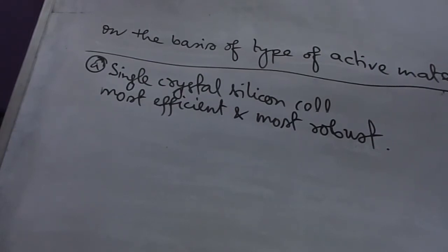The first step is the production of metallurgical grade, 99% pure silicon, MG-Si, from its ore SiO2 by reaction with carbon in an arc furnace. The energy cost of this step is 50 kWh per kg of silicon. Huge energy. The most common commercially produced silicon cell has an N on P structure, where the base material is P-type, which has a thin diffused N layer on top of it.